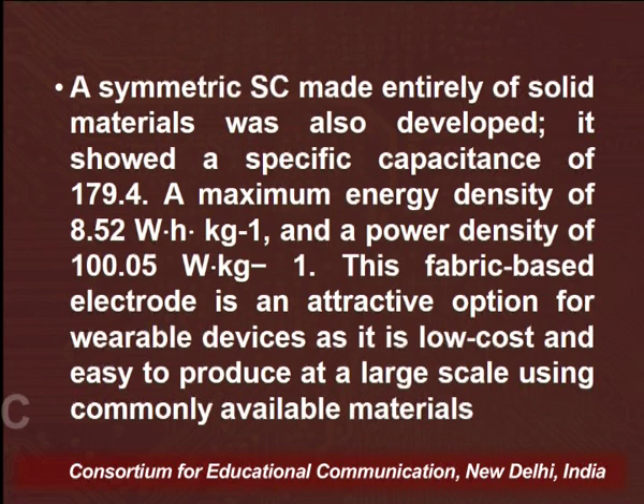This three-dimensional effect in the fabric electrode results in a good charge discharge performance with a specific capacitance of 197.4. That is a good score for the charging discharging performance. A symmetric supercapacitor made entirely of solid material was also developed, and it shows a specific capacitance of 179.4, a maximum energy density of 8.52 and a power density approximately equal to 100.